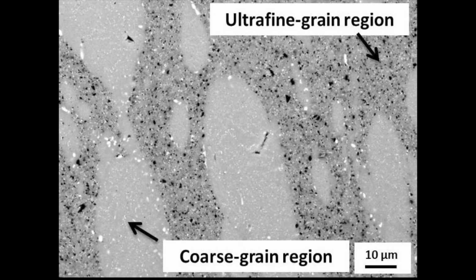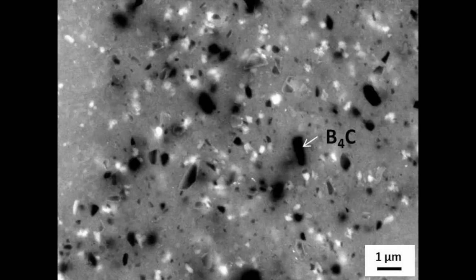The bright area is the coarse grain region, which contributes to the ductility of this material. The dark area is the ultrafine grain region reinforced with boron carbide, the hardest material in nature after diamond and cubic boron nitride. This region gives it extraordinarily high strength compared to conventional aluminum alloys.